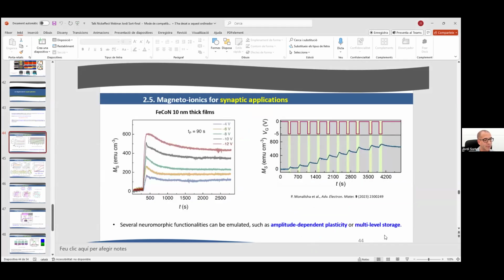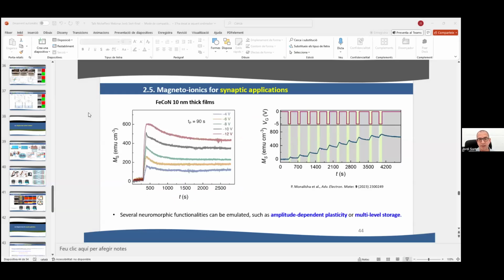Well, there is reversibility actually. For example, you can see in, do you see now this one, for example? Here you can see the reversibility that happens in several of the slides. But for example, here, it is reversible, but here it's just at 0 volts. So here we apply voltage, we induce some effect, we stop the voltage, and then it goes down. But later I showed you this complete reversibility applying voltage of opposite polarity. So this, for example, we induce at -8 volts, and then we apply positive 8 volts, and we have full reversibility that we can do even at 1000 seconds.